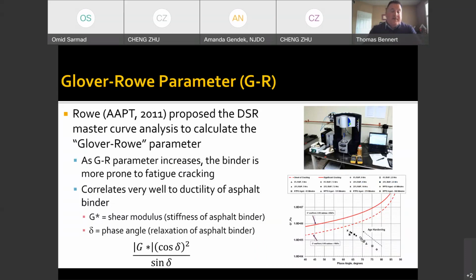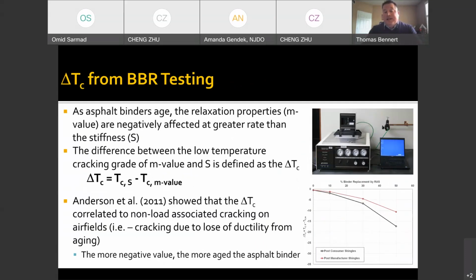If you have excess amount of material that you can get, you can also run the same level of testing in what we call the bending beam rheometer. This is the traditional test that's used in Superpave binder grading for low temperature properties. And what we see here is that we look at this delta T sub C, and that gives us a relative idea of how the relaxation properties of the asphalt binder are being lost, typically over time, oxidation aging, or by use of too much recycled product, shingles or RAP. Both methods work fairly well, but the first method, Glover-Rowe, you require a lot less material to use, so it's a little bit more conducive to very quick forensic type work.